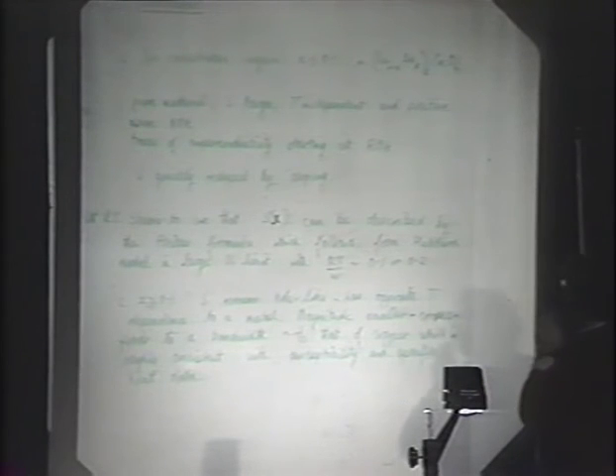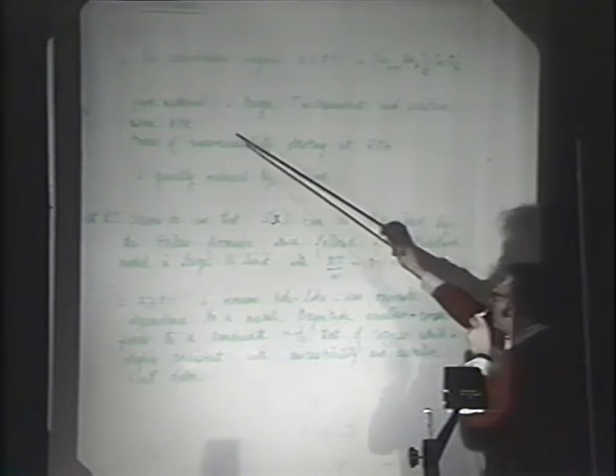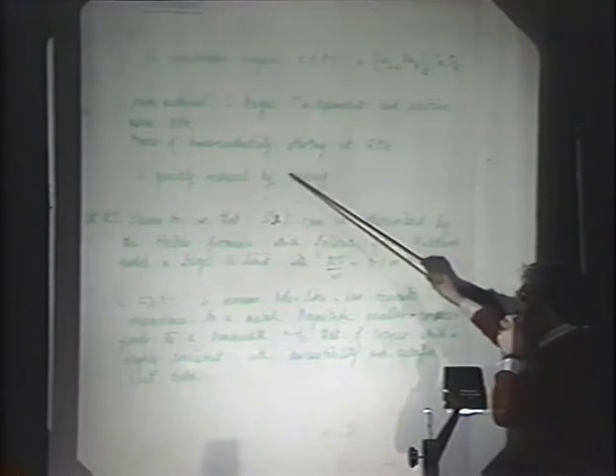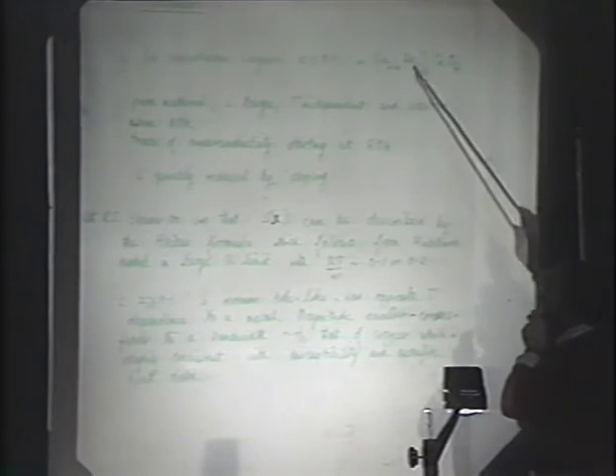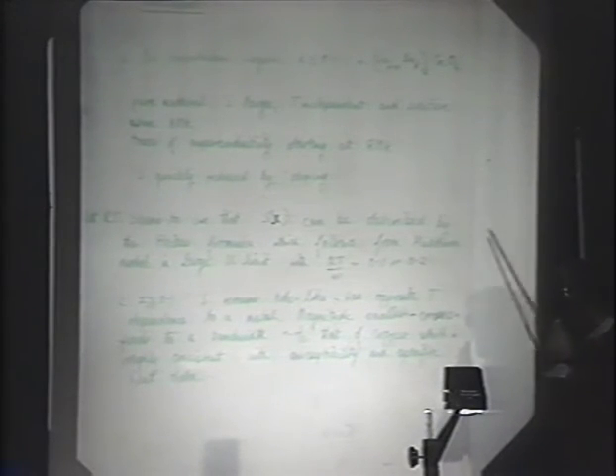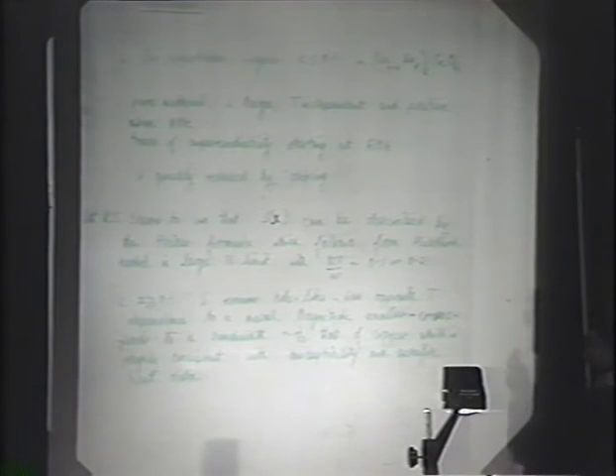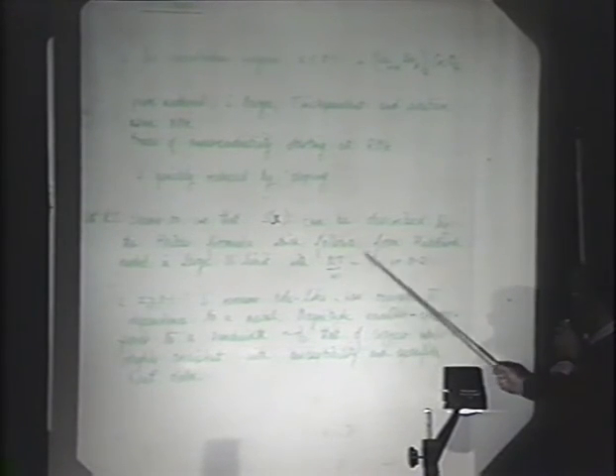So in conclusion, in the low concentration regime, pure material, thermal power is very large, T independent and positive. This is all above 80 K. Below 80 K there are traces of superconductivity. S is quickly reduced by doping. At room temperature, it seems to us that S, thermal power as a function of concentration, both in barium and strontium alloys, can be described by the Heikes formula, which follows from the Hubbard model in the large U limit. That means only 1 electron per site or less, with kT over W of the order of 0.1 or